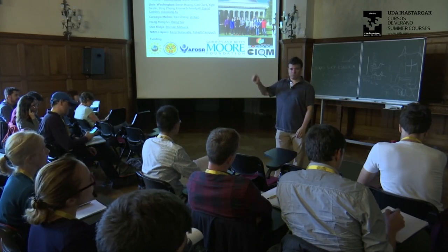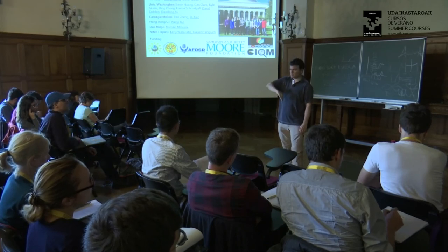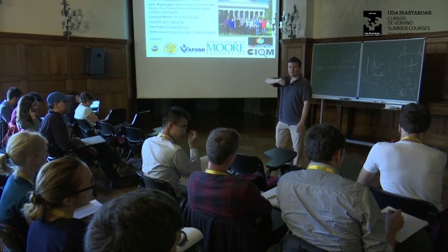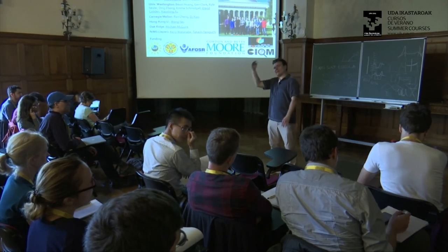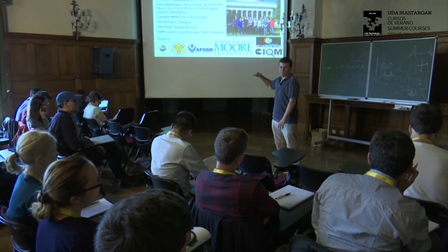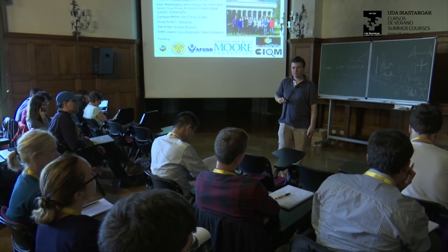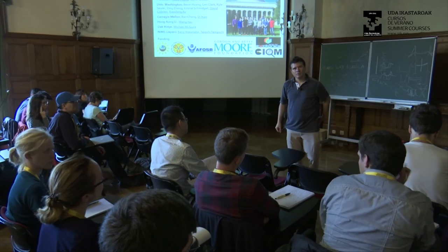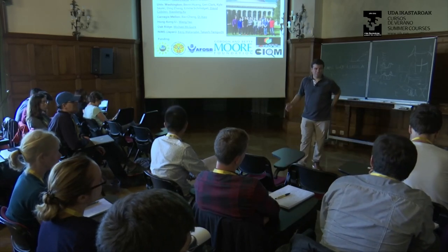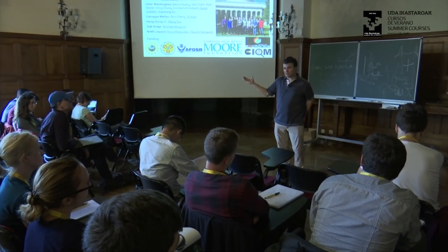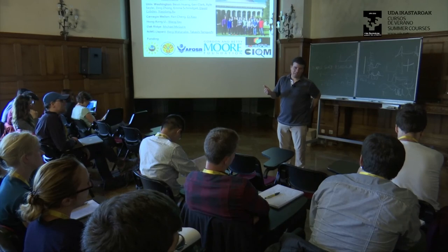Yes, we just dial the gate voltage, okay? And then we see that it becomes a superconductor, and the Tc increases with gate voltage. We haven't been able to go all the way with gate voltage to see if we have a dome or it just monotonically increases. That we don't know, because we couldn't go beyond a certain gate voltage value, okay? Oh, we don't know. It's a system that, you know, there are many materials that when you dope them, they become superconductors. This is one of them. We do not know what is the nature of the superconductivity, the order parameter, etc.